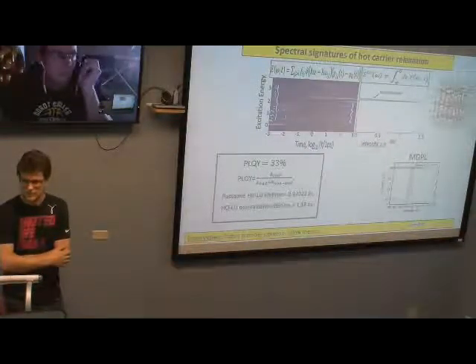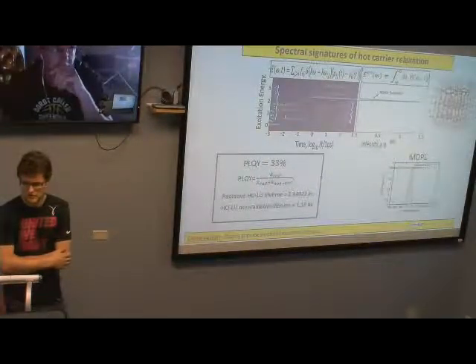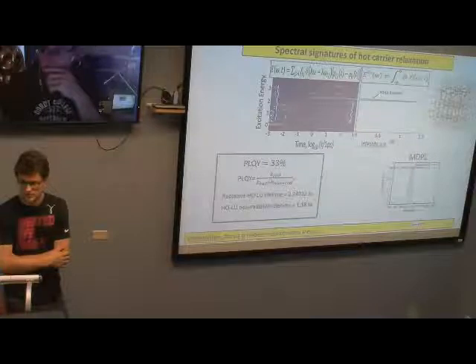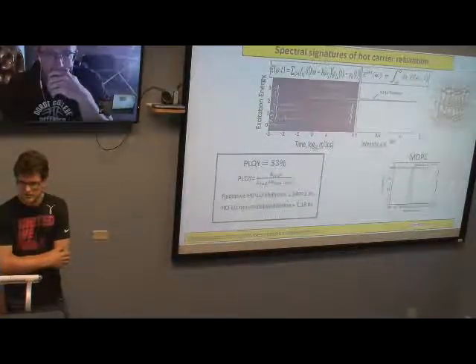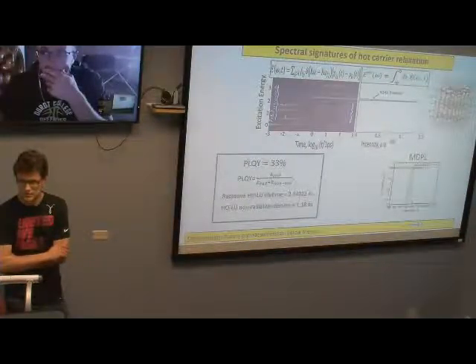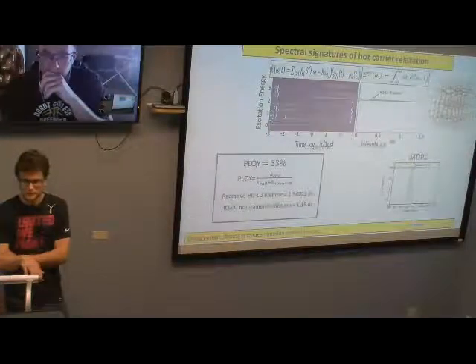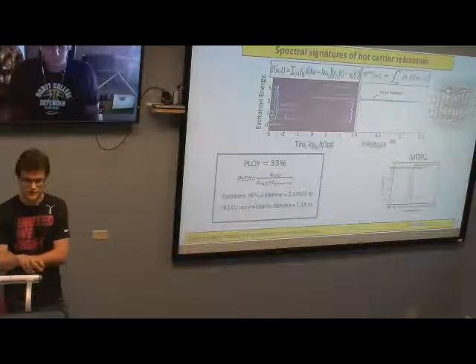Will those correspond to more realistic non-adiabatic couplings? No, for MDPL you do not need non-adiabatic couplings. You need just sampling of the oscillator strengths along the trajectory, but you can make several trajectories at different temperatures and make MDPL spectra at different temperatures and see how the line width depends on temperature, on one side, and dependence of line width on temperature from experiment on the other hand. I get that. I just didn't know if we ran our simulations at 300K, whether that would overestimate non-adiabatic couplings for room temperature. It was just a question. I don't know.